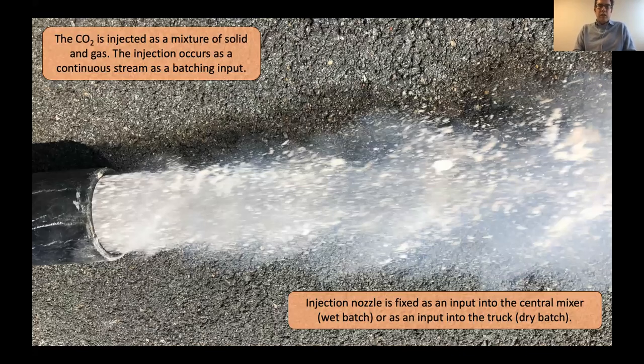We take a supply of liquid CO2 from the industrial gas suppliers, and a tank of liquid CO2 is set up at the concrete batching plant. But liquid CO2 is not stable at atmospheric temperature and pressure, so when the CO2 actually gets to the concrete, you have a mixture of solid CO2 flakes and gas. Over a period of about 30 to 90 seconds during the mixing phase, the CO2 is injected into the concrete. This retrofit involves just putting the injection nozzle someplace where the concrete is being mixed. It's either a central mixer in what they would call the wet batch process, or the truck itself, if the truck serves as the mixer.